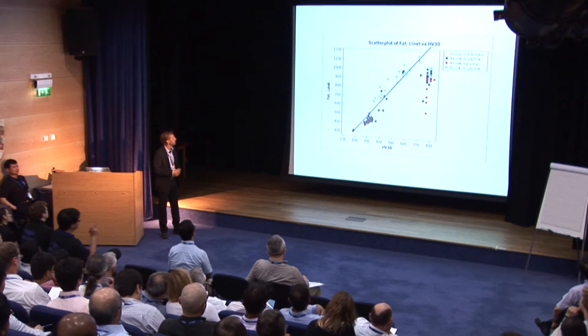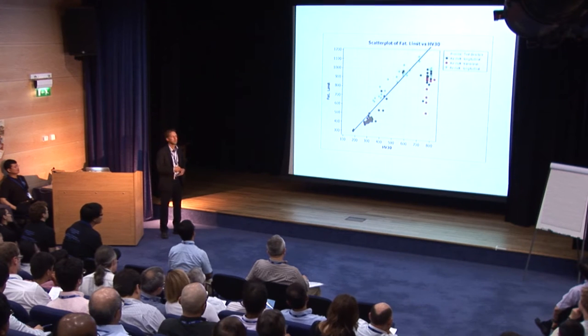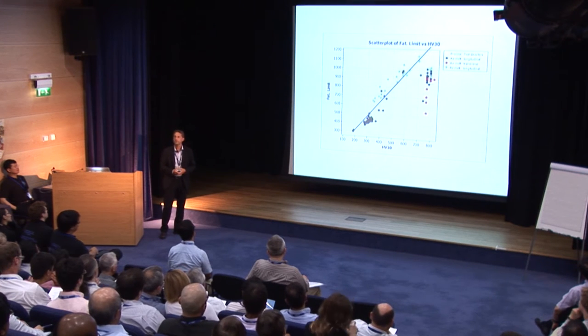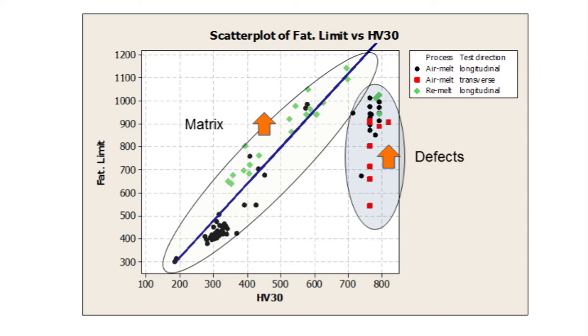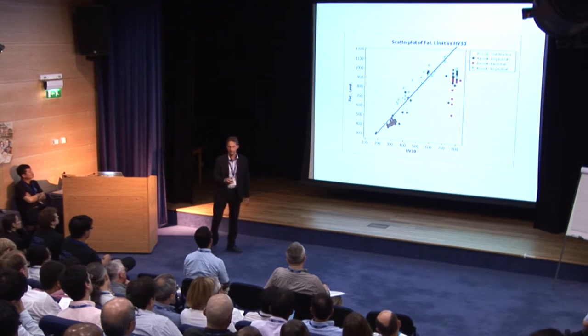One rule of thumb is that the fatigue strength, here looking at the very simple rotating bending fatigue, is proportional to the hardness, which is a way of expressing the strength. And of course, you see this correlation is quite good, but it starts to deviate. What we would like to do is develop and work with material up at this point, where it starts to deviate.